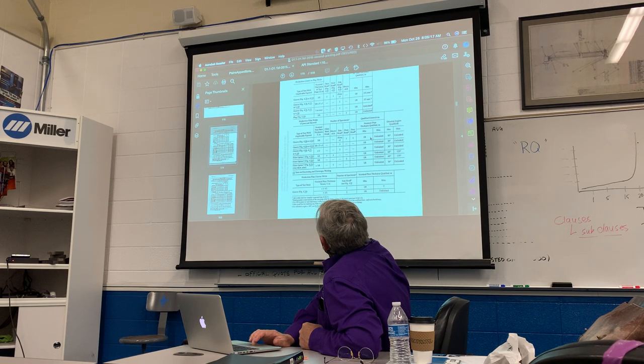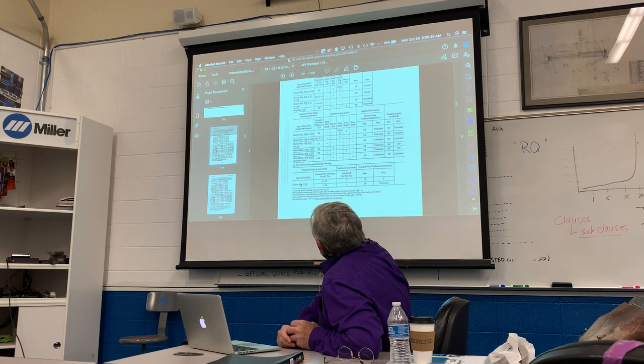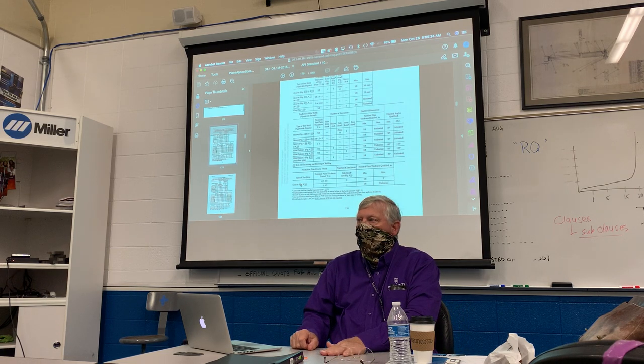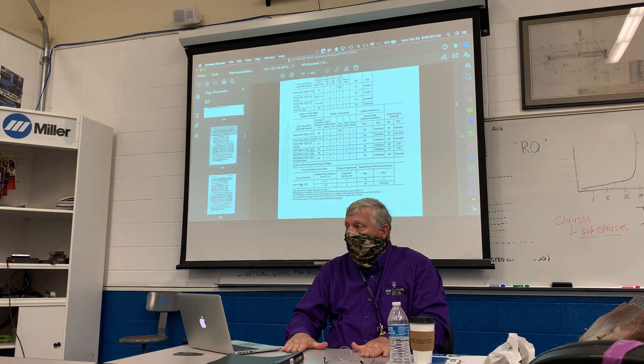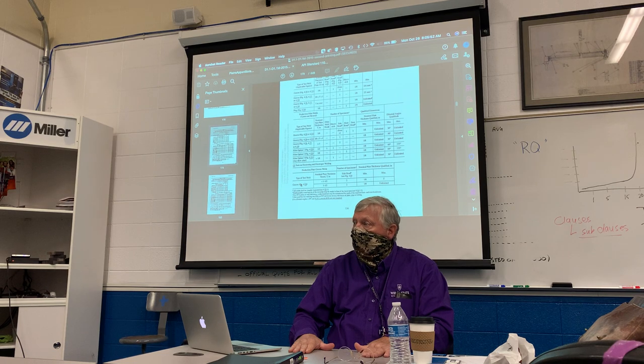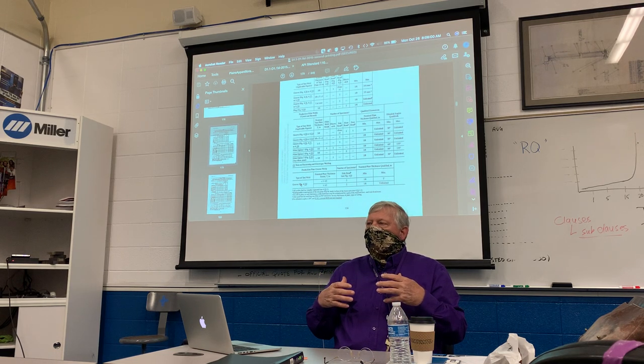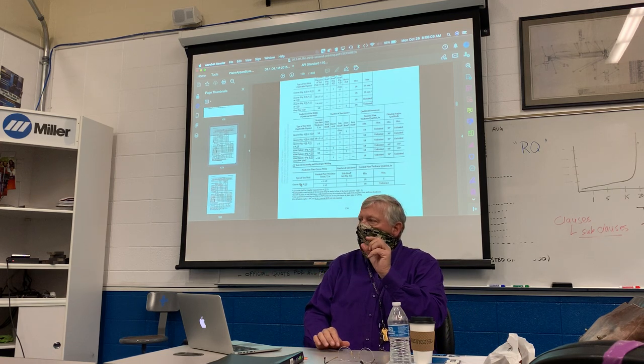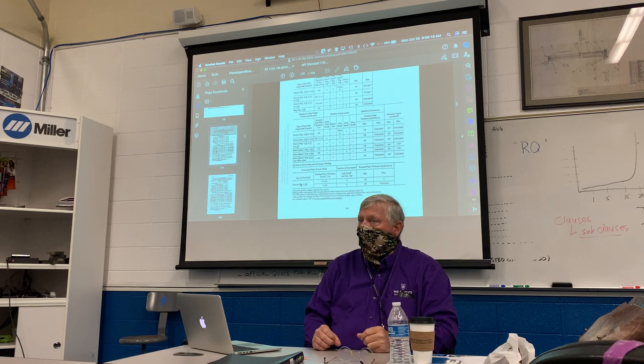Notice there's a footnote D — it says this also qualifies for welding any fillet or PJP weld size on any thickness of plate, pipe, or tubing. So if you do that half-inch groove test and the two side bends pass, this welder is qualified to do one-eighth to one-inch thick, all fillets, and all partial joint penetration grooves. That's a pretty wide-ranging qualification. I like to get welders to test so they get the widest range — one test in the vertical and one in the overhead gives you pretty much an unlimited welder until you get over one inch.